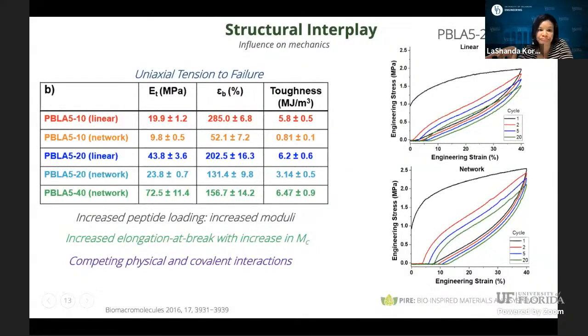Now, also very important here is that, of course, the linear systems tend to have higher overall mechanical properties than that of the network systems, except for the 40 system. And that's because of the way we're able to build up the overall microphase segregated structure. On the right is just a comparison of some hysteresis studies, cyclic experiments. You can see here that based on these competing physical and covalent interactions, you have very different hysteresis behavior.